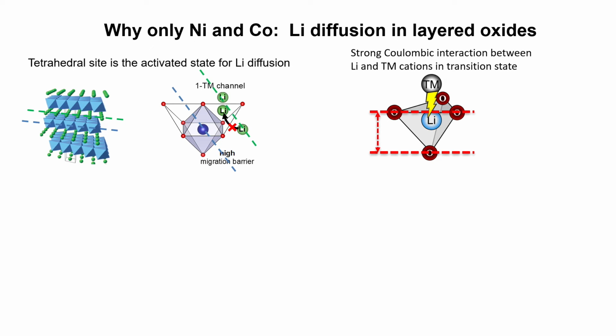And when you look a little closer at that configuration, this is actually the activation barrier for diffusion. You are in close contact with a high valent transition metal, so you have a lot of electrostatic repulsion, and that's what sets your activation energy. So now you can see that if you reduce the spacing of these layers, the activation energy shoots up.